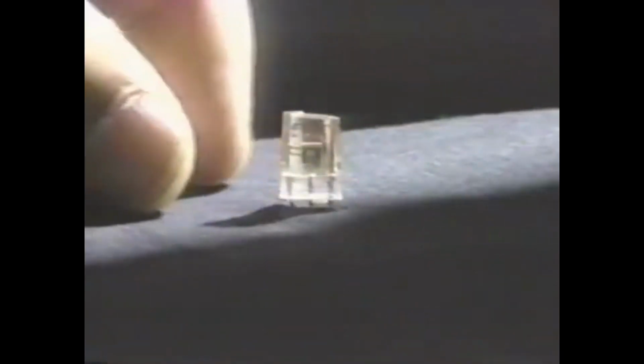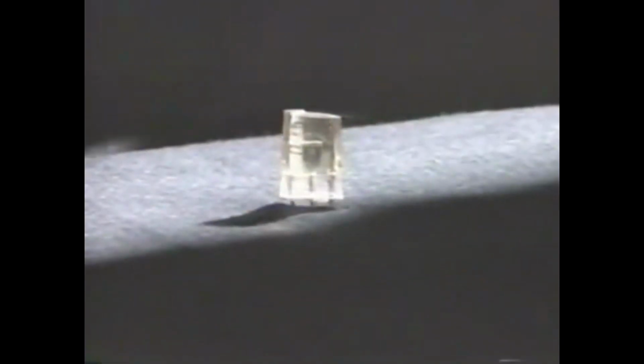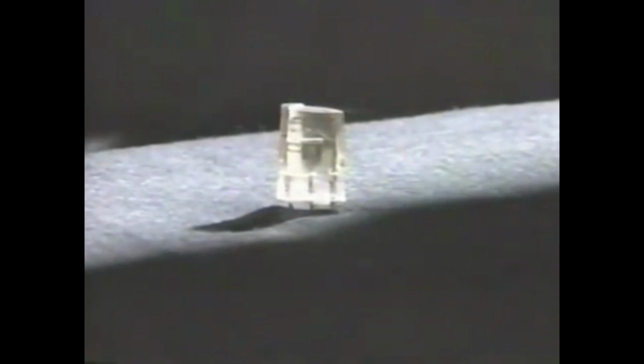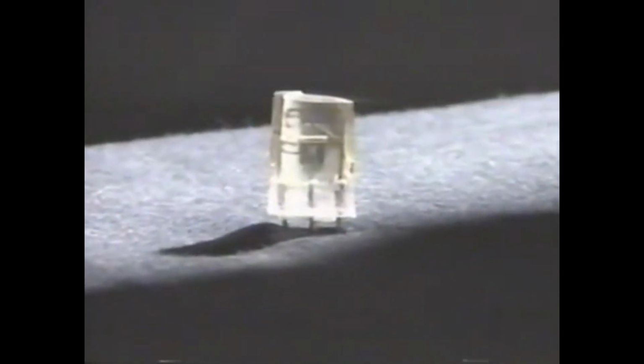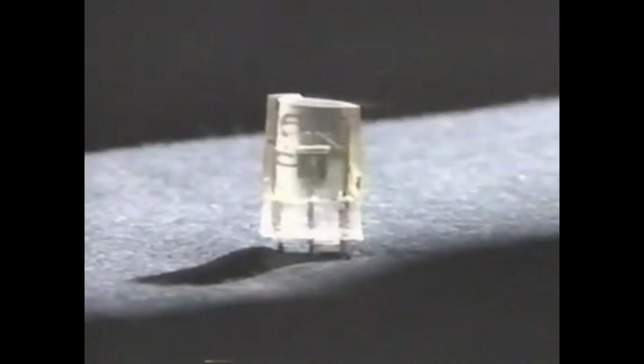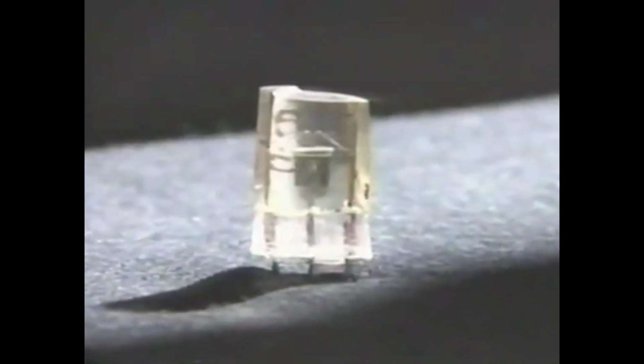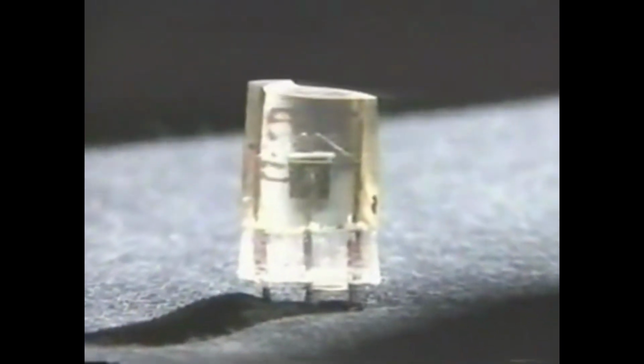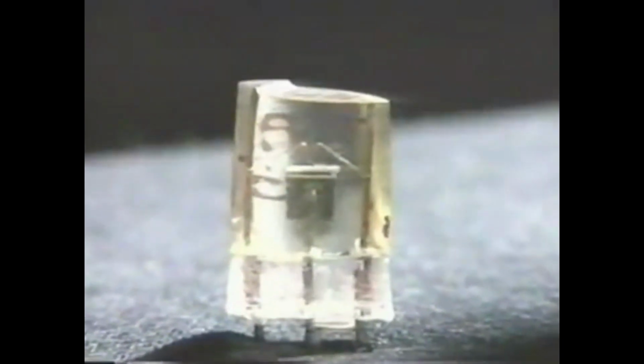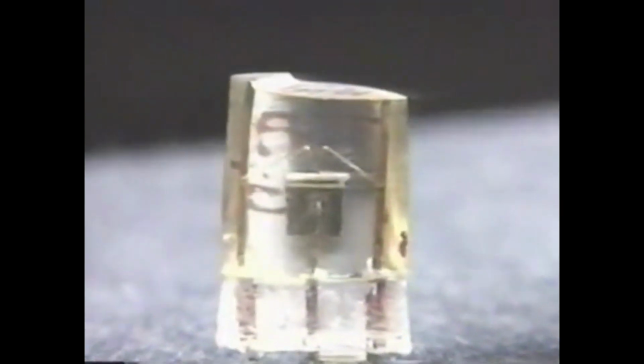They then tried firming the needles with resin. This is a test-manufactured product sealed in plastic. Through the transparent resin, two needles contacting the small germanium crystals can be seen. However, due to changes in weather, the resin repeatedly expanded and contracted, and the needles finally slipped out of position. In the end, RCA abandoned mass production of the point contact transistor.